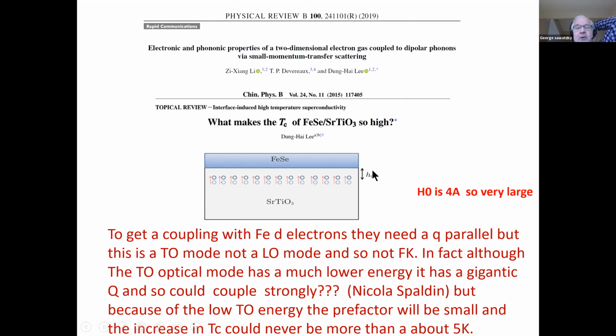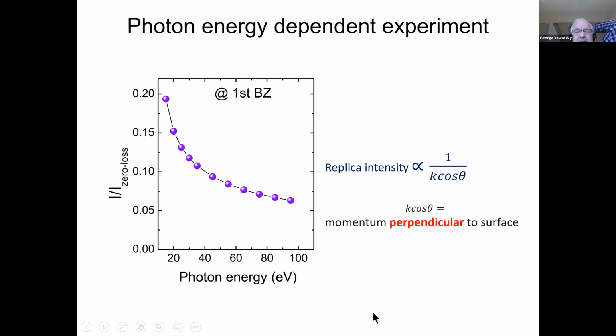The Q parallel is 0, but it starts coupling for these oscillators with a Q parallel which is finite, okay? However, you have to be careful with that, because if you have a Q parallel, then this is not a longitudinal optical phonon anymore. It's a transverse optical phonon. And the energy of the bulk transverse optical phonon is at 15 or 10 milli-electron volts. So in fact, although the transverse optical mode has a much lower energy, it has a gigantic Q, so it could couple very strongly. However, the...